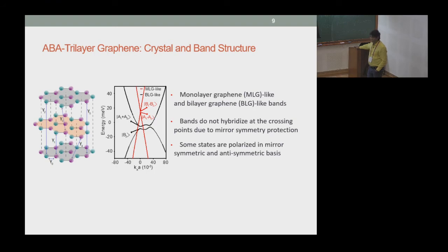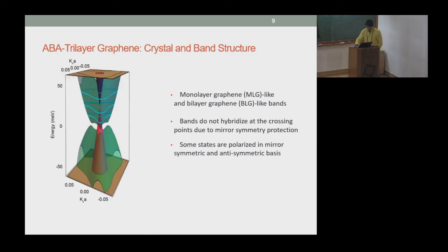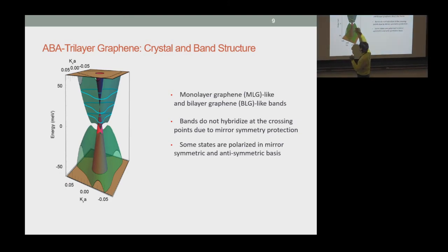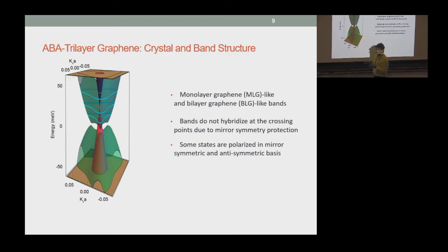We measure resistance effectively, yes, as a function of magnetic field and density of charge carriers. Just to explain, one effect of the magnetic field is that you start to make the density of states not continuous, but you form orbits. That's one knob. The other knob is I can tune the Fermi energy on demand. I can fill up the electron cell here, here, or here, or above. That's completely under my control.